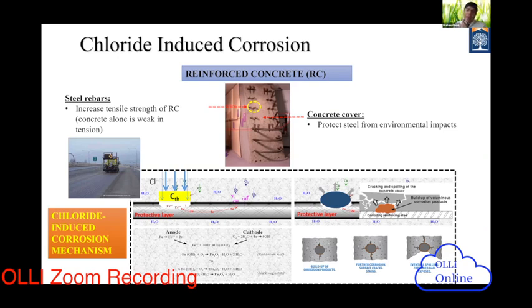So after a certain amount of time, you can imagine that rebar can handle up to a certain level of chloride content, which is coming from the salt. If the chloride amount exceeds its handling capacity, then obviously the corrosion initiates. One of the key parameters we call the chloride threshold, C sub th. Basically, that's the limit, the red line or red flag. That is the maximum amount that can be handled by the rebar. Different rebars can handle different chloride threshold amounts. Sometimes we use better rebar so that it can handle a higher chloride threshold.